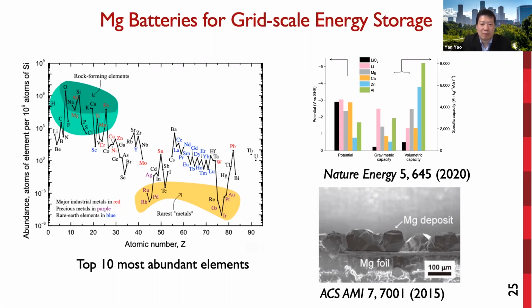So this is in sharp contrast with lithium metal growth behaviors. However, in recent years, reports have shown magnesium also forms dendrites when the electrolyte is not fully optimized to have the highest coulombic efficiency.